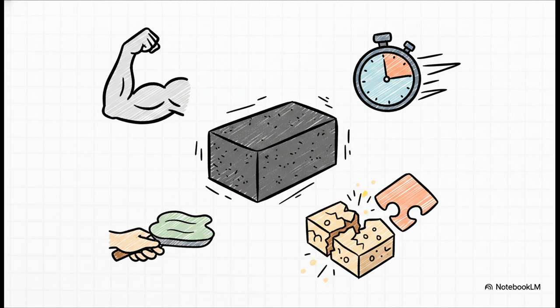But you really gotta watch out for the trace risks. Too much lime, magnesia, or sulfur causes what engineers call unsoundness, which is a ruinous volume expansion that literally cracks the concrete from the inside out. No way do you want that. And excess alkalis, they cause those ugly white spots called efflorescence that you sometimes see on brickwork.